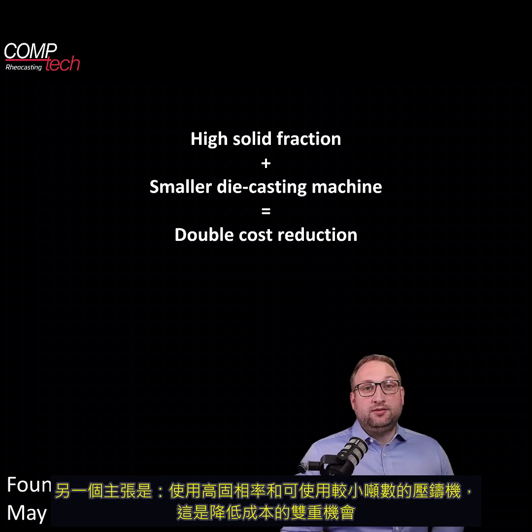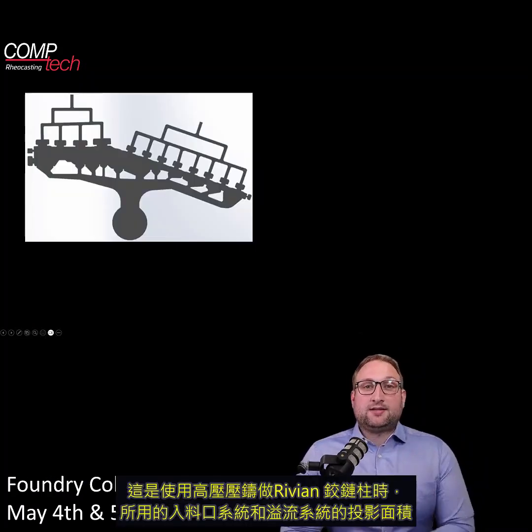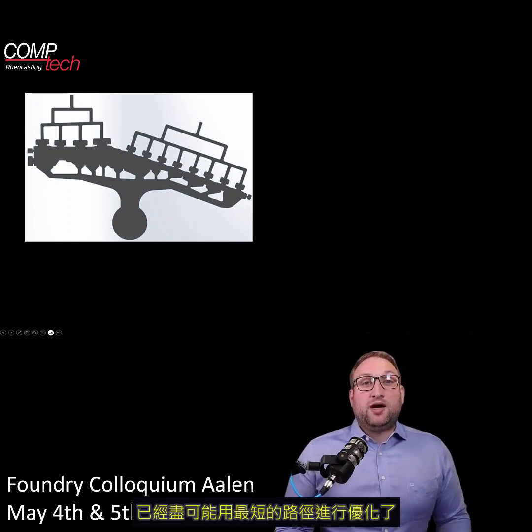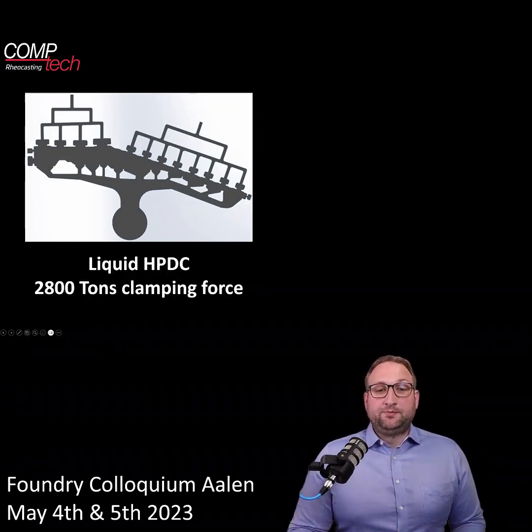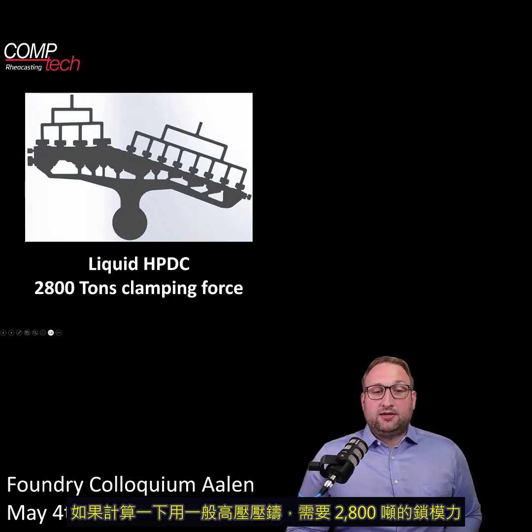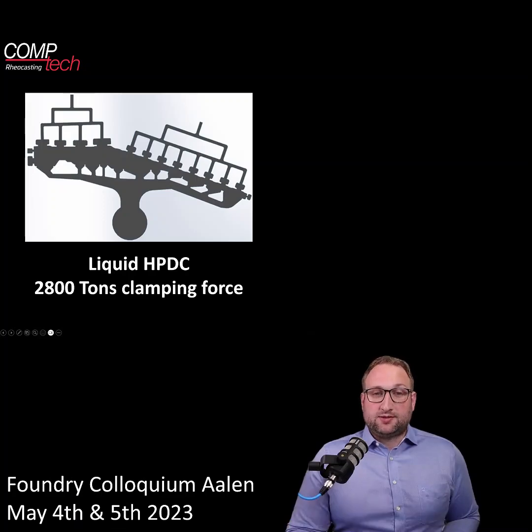Another claim is that a high solid fraction and a smaller die casting machine are a double shot at cost reduction. Here I can show you. That's the projected area of the Rivian hinge pillar in between here with a high pressure die casting in-gate system and overflow system, optimized for the shortest way possible. If you calculate that for high pressure die casting, it's 2,800 tons of clamping force.